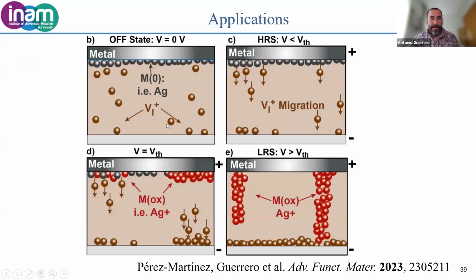This is how we understand the system working when we use silver, for example. We have the background density of defects of halides. The halides can migrate following the electrical field. At some threshold voltage, we will induce the electrochemical reaction of silver 0 to silver 1. So we get the silver charged. And then at voltages higher than this threshold voltage, the ions will follow the electrical field, making conductive filaments. Of course, because these ions are oxidized, they can go to the top or to the bottom, depending on whether the voltage is positive or negative. So we can break these filaments, or we can form them.